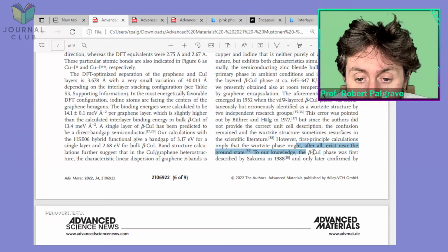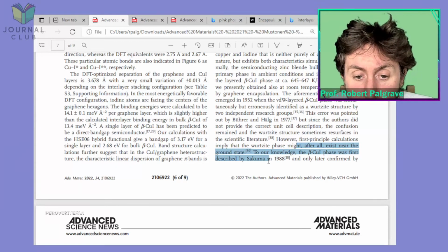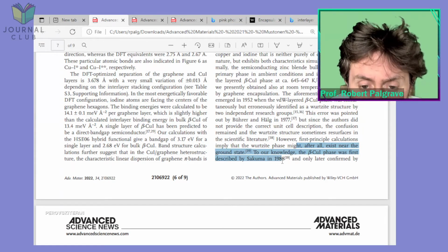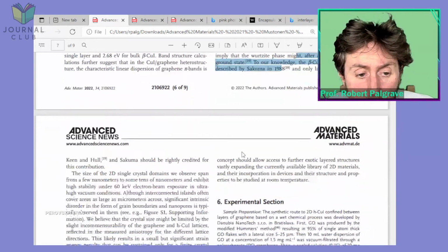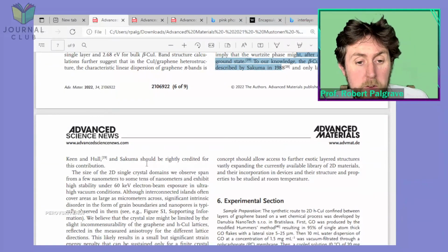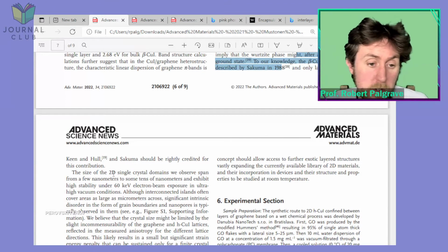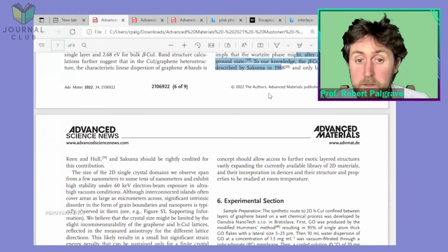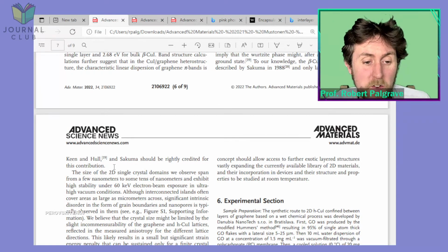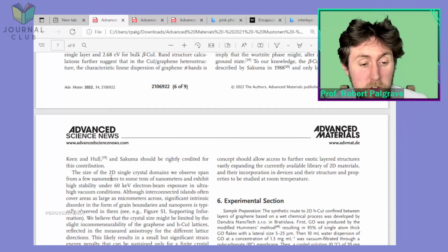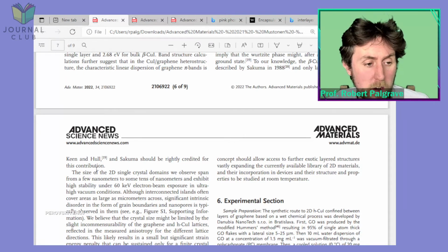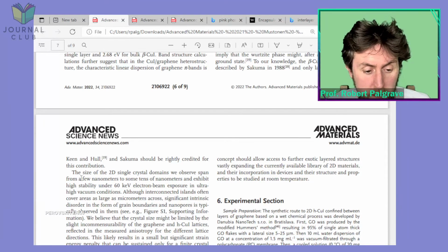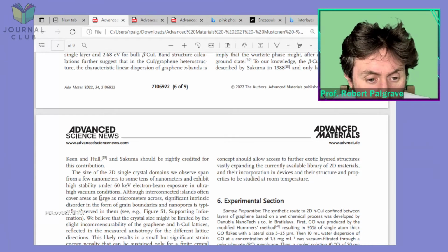To our knowledge, the beta cuprous iodide phase was first described by Sakuma in 1988 and only later confirmed by Keen and Hull. Sakuma should be rightly credited for this contribution. Okay, so there's some interesting historical information on controversies about the structure of this material. Maybe I'll grab VESTA. I wonder if I have VESTA open actually, and look at those things in a minute.